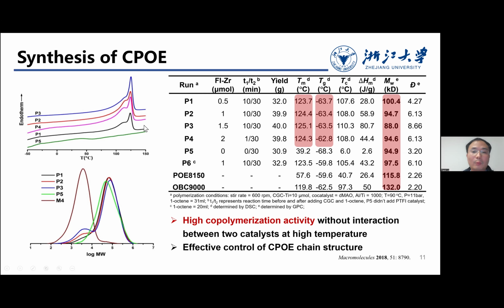So for the copolymerization, you can see here we can observe the very broad melting peak of these copolymers. That means we already copolymerized these macromonomers with our alpha olefins, octene, and also the ethylene. Here you can see the high melting temperature from the crystal part, and the low glass transition temperature from the amorphous part. In this way, we synthesize the copolymers with a molecular weight larger than 100,000 gram per mole. And we also have high copolymerization activity here. If you check the GPC curve, you can see there is still a little bit of macromonomer residue on this part, and here we have a huge copolymer.